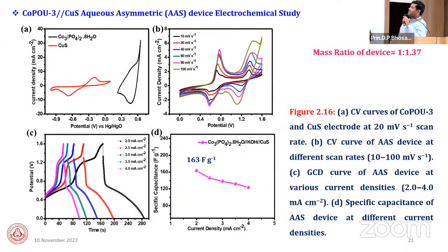Okay, now I'm preparing the cobalt phosphate as a positive electrode and copper sulfide as a negative electrode using an aqueous device. It means a solution electrolyte, two electrode cell system. This is the CV graph of positive and negative electrodes in the negative potential window for the negative electrode and the positive potential window for the positive electrode. Then I calculated CV and charge discharge of this aqueous device in 1 molar KOH electrolyte for different scan rates and different current densities for the 1.6 potential window.